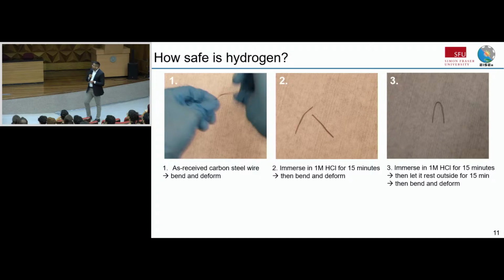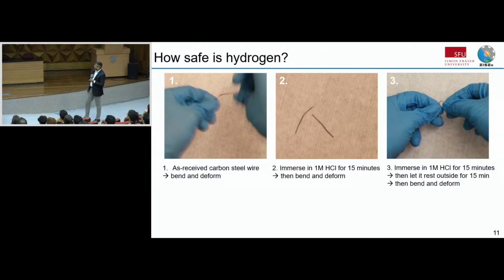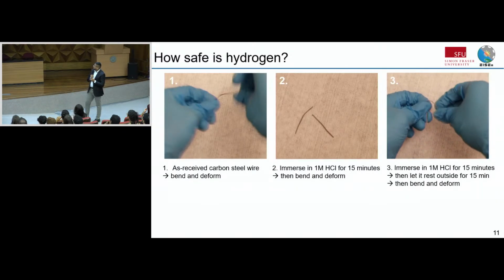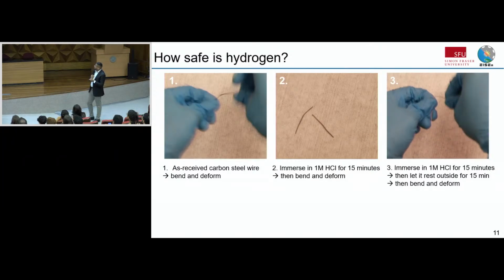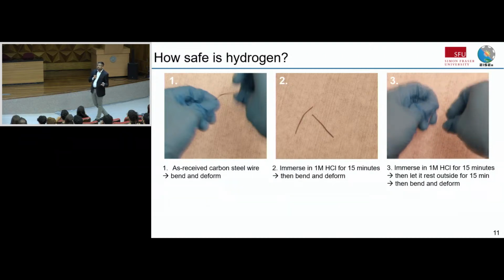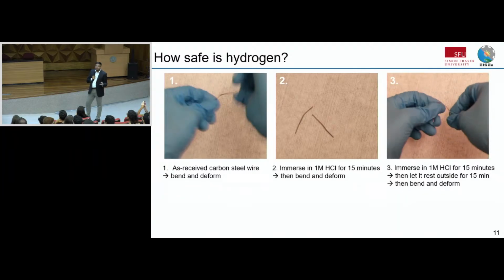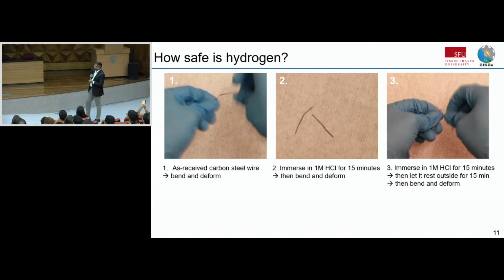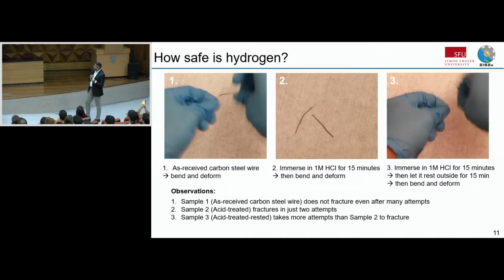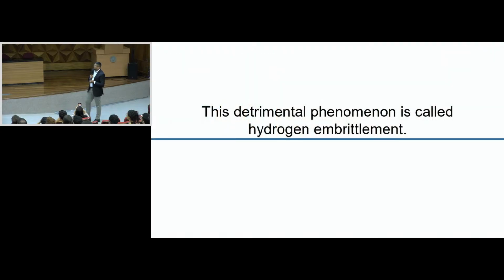So, if you're thinking what's going on, it's probably corrosion, it's eating up the metal. That's true, but then this interesting thing happens, right? If you take the wire out of the hydrochloric acid and let it sit outside for 15 minutes, and then you do that test again, you see that it's not breaking. In this video here, it broke in just 2 seconds. Here, it's not breaking. That means it's regained its strength, right? So if it was corrosion, this wouldn't happen because corrosion is permanent. Just to summarize the observation, the first video doesn't fracture, the second one fractures right away, the third one takes many attempts to fracture. So what this is called is hydrogen embrittlement.